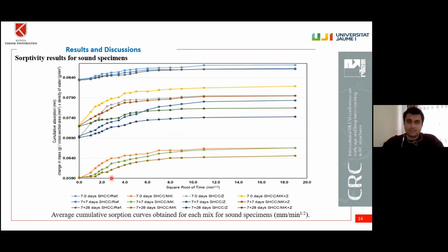Here we can also compare the sound specimens in terms of the sorptivity test. As you can see from the lines, these lines belong to the reference specimens. The use of all mineral admixtures significantly reduced the sorptivity index of specimens. Why? As I said in the beginning, first is the pore size refinement and grain size refinement with the presence of mineral admixtures. However, among the mineral admixtures, metakaolin most reduced the sorptivity index compared to the others. Also, the presence of zeolite in both forms shows a similar sorptivity index.